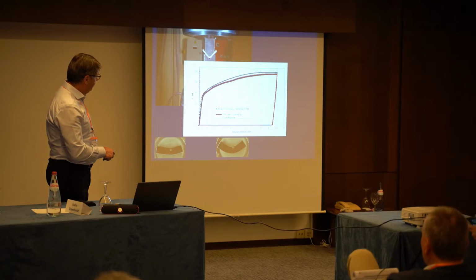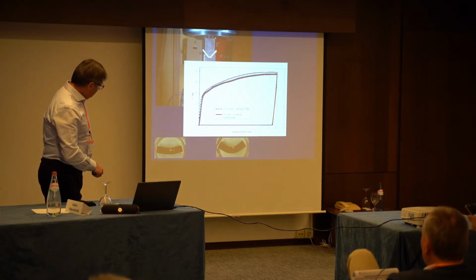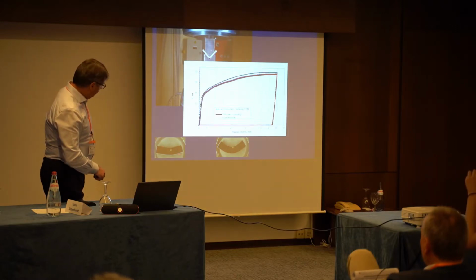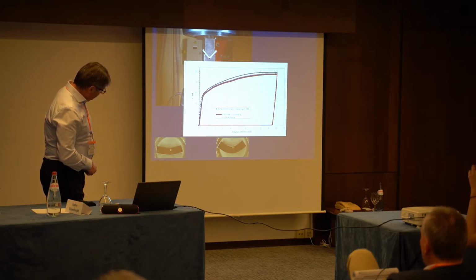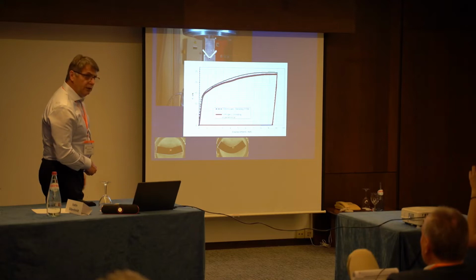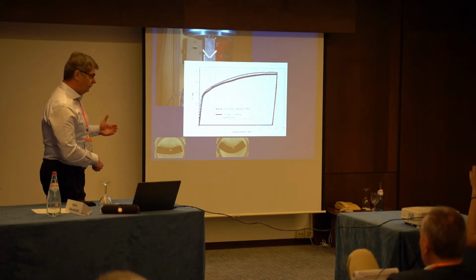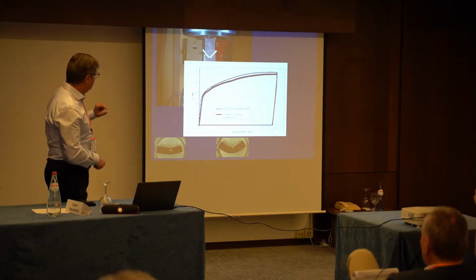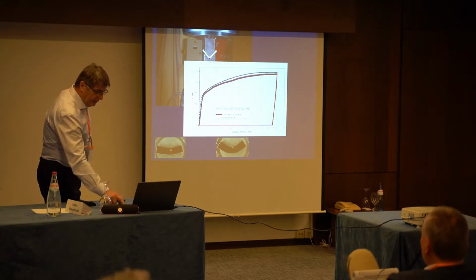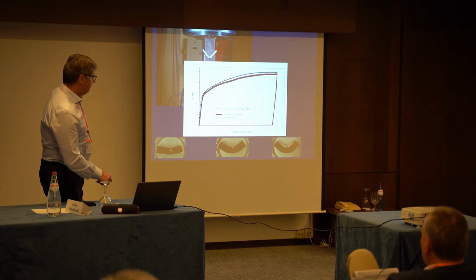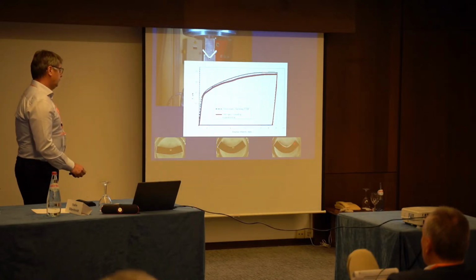This was actually the last, highest deformation bend point. You see here the metallographic samples, where we have measured in this peak point the hardness over this section in order to determine the concentration of the martensite over the section. This is actually cut as a small piece. And here we have also the third part, which is 50 millimeters of deformation.